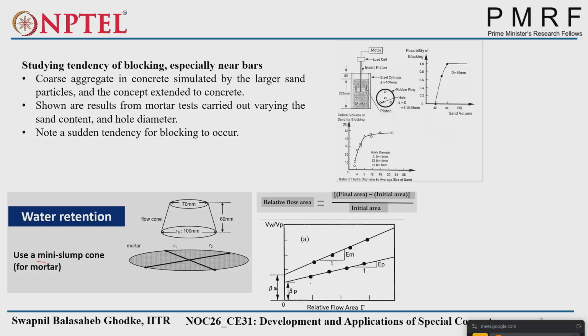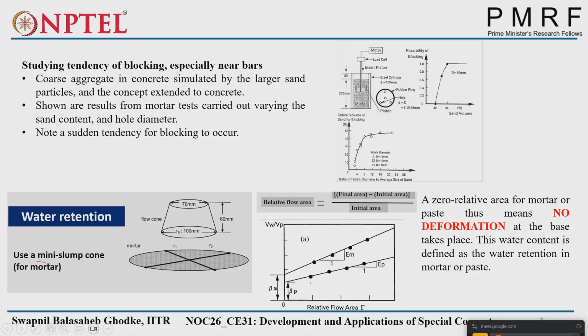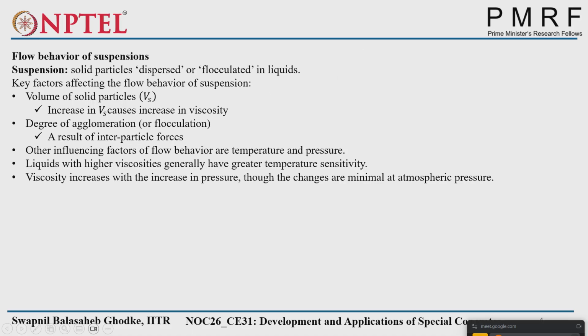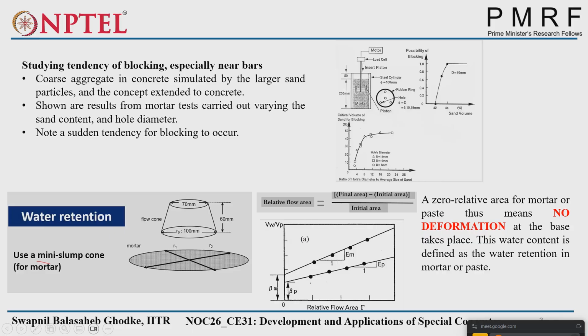It indicates that at zero flow, a certain amount of water is already there, right? Water is there, but that is not allowing flow. That is water retention, because zero relative area for mortar or paste means no deformation. We are not observing any deformation. That's the zero flow area. At best, this water content is defined as the water retention in the mortar or paste. Once the critical value of water retention is exceeded, only then does flow start. Excess water alone allows the flow. So that's why these values, beta M and beta P, are important. And the slope of the mortar graph and the paste graph indicates the sensitivity of that particular flow.